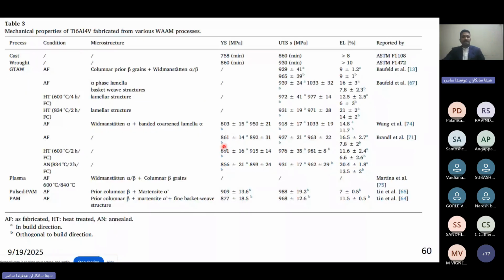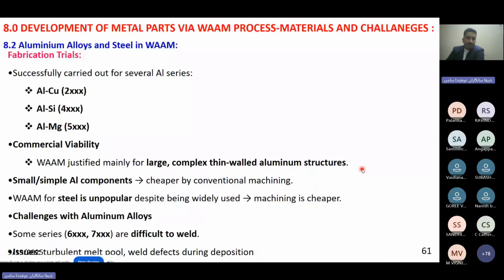Okay, you can see several people developed a WAAM product from the titanium 6Al-4V alloy. So most of the people observed columnar structure or lamellar structures, and they have tried to compare to the cast counterpart. Some people have achieved, even more than the cast counterpart. But the only drawback they observed is anisotropic behavior: yield strength, ultimate strength, elongations. Then aluminum alloys and steels.